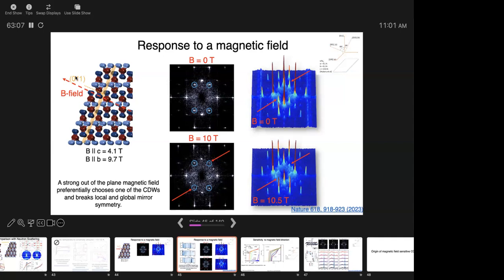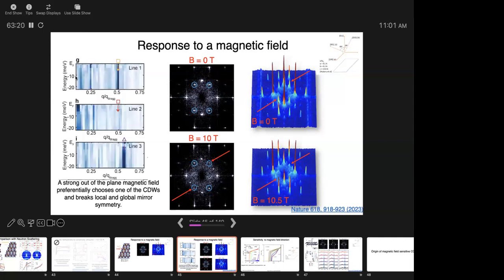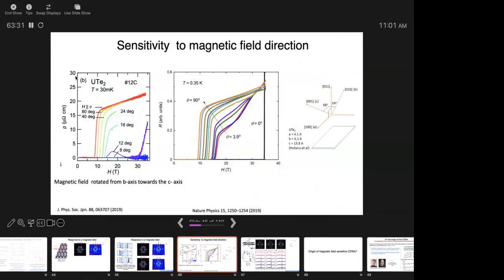So first, the magnetic field breaks this mirror symmetry, which makes sense actually. But the important thing here is that these peaks are getting highly suppressed. You can see it in the line cut as well. In this direction, you can hardly see this peak anymore. These two peaks have gotten pretty suppressed. Okay, now we know,